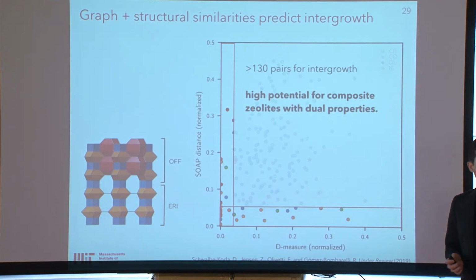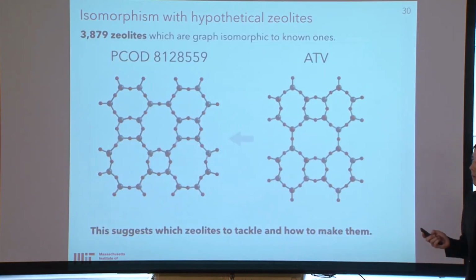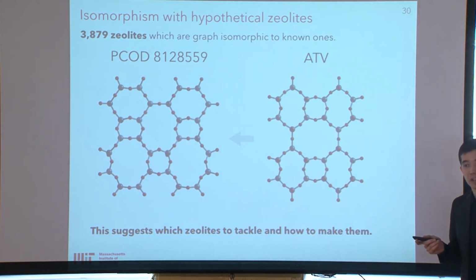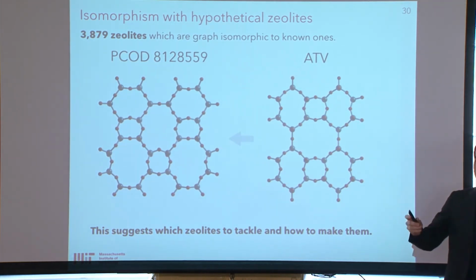Finally, if we go to all those databases of hypothetical zeolites, that is, zeolites which have been enumerated by computer predictions, we found more than 3,900 zeolites which are graph isomorphic to known ones. This means that for each one of these hypothetical zeolites, we pointed to one known zeolite, which can give us a clue on how to make these hypothetical ones. And this opens a new venue to synthesize zeolites faster and in a theory-guided way.